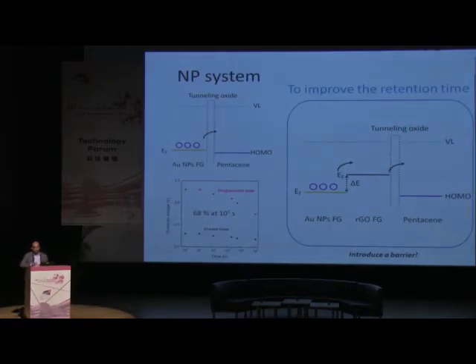Now, still there's a problem. Why? If you see the structure of these devices, the work function of the nanoparticles matches well with the HOMO level of the molecule that we use. So even though you have a tunneling oxide, the charges can still get back. So what you are going to do is, there comes graphene oxide, or reduced graphene oxide, which is basically graphene. We artificially create another barrier so that the charges cannot easily get back. So we put a layer of reduced graphene oxide to stop these charges from getting back.